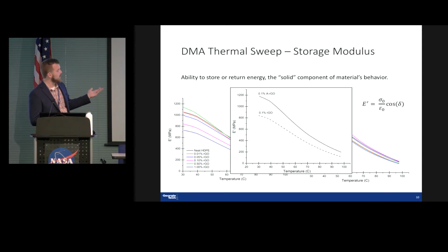But to kind of quantify how much of a difference there is, I picked out the two lines of 0.1 weight%, the same samples I showed earlier. And if we look at the alkylated version, we're seeing almost 50% increase in the storage modulus of that sample versus the unmodified reduced graphene oxide. So this is a good sign. We're having a good impact here. And something I forgot to mention is that we studied these things up to 100 degrees C. The inspiration for doing that is that it replicates the environment that they would see on the lunar surface, at least on the high temperature extreme.